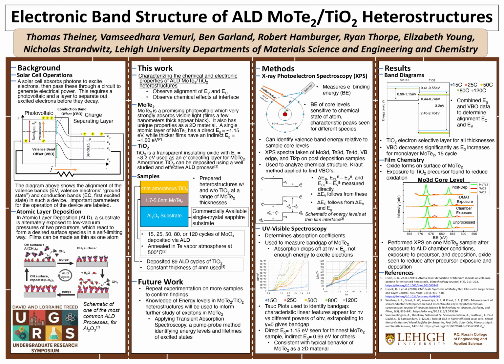And then if you get core levels at a heterojunction sample where you have two films on top of each other, and then you also know where the valence band lies in each of the materials relative to the core levels, that can allow you to figure out this alignment of bands that we're saying is so important for determining how a photovoltaic device acts.